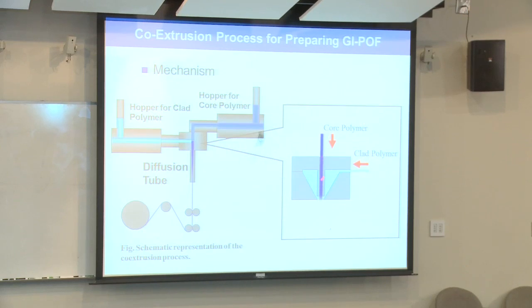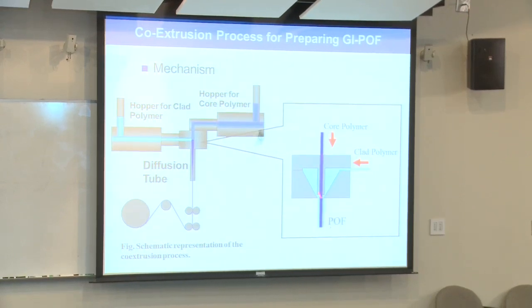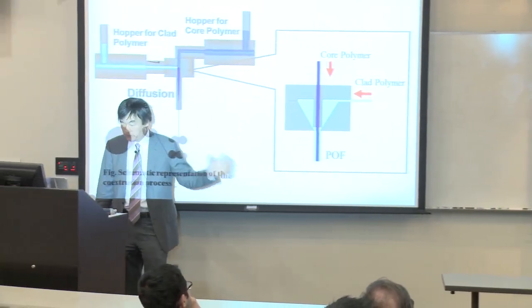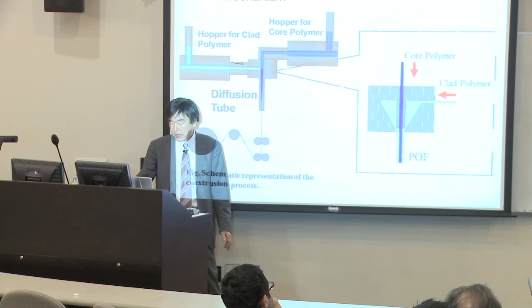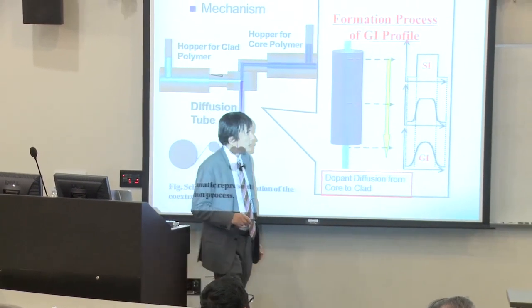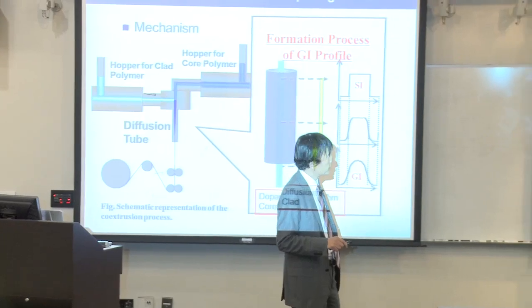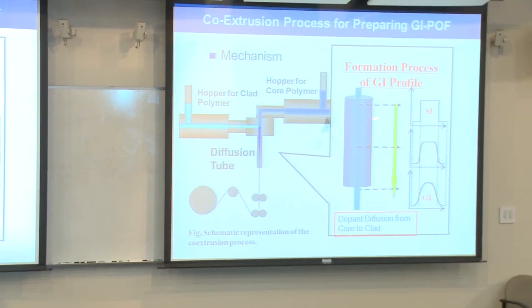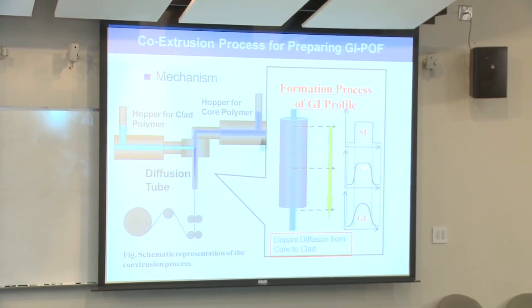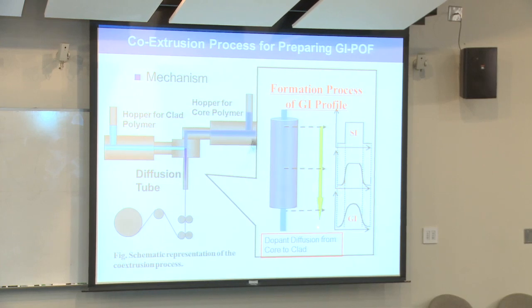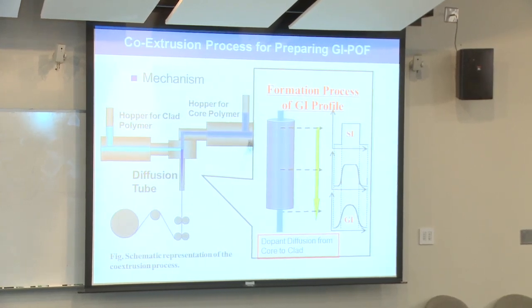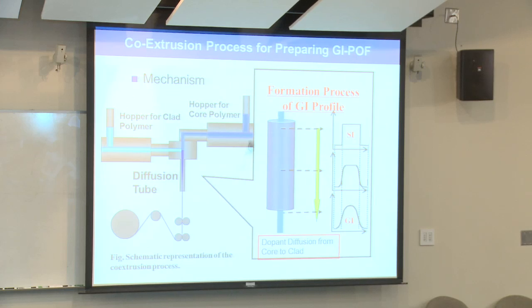Core polymer and clad polymer are simultaneously extruded in this die. The core polymer includes small dopants having higher refractive index, a homogeneous dopant. Then right after the die, here the index profile is just like a step index. But during the diffusion tube, dopants start to migrate to the periphery region to form the graded index profile. So the process is very simple.